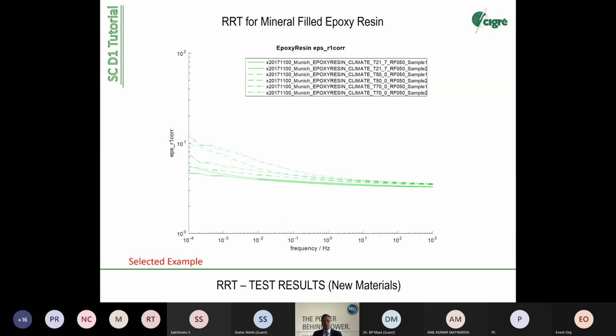And why? This is also the case with the different temperatures. The reason is simple, because this material was a high quality commercial grade using fillers of low alkaline content, low sodium. Sodium is the main contributor to the problem. Potassium is not so critical because it's not fast moving, but the speed of ions is higher with the sodium. So you have to take care that your fillers have low sodium content. And secondly, the fillers must be treated with silane at the surface. Silanization and alkaline content makes a good filler for a good composite material.